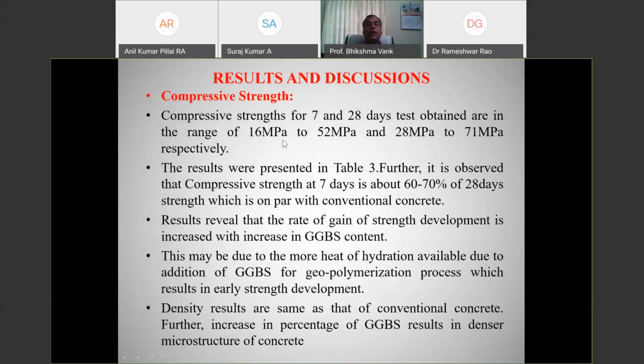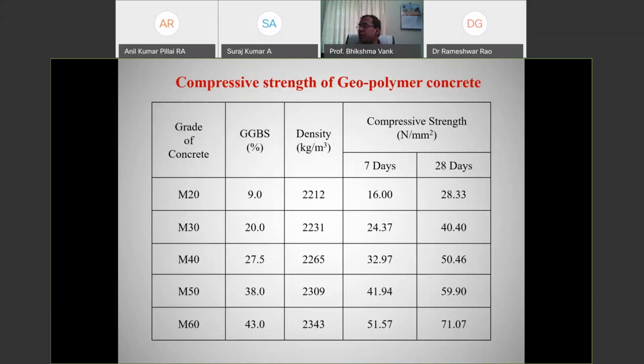And compressive strength values have been obtained for several mixes. 28 MPa for M20, and the other value we got for M60 is 71. You can see here that the 28 days compressive strength for M20 is 28.33, M30 is 40.4, M40 is 50.46, M50 is 59.9, and M60 is 71 point something.